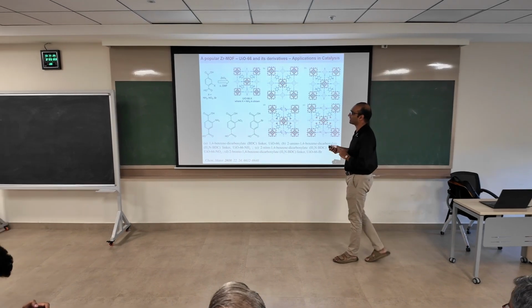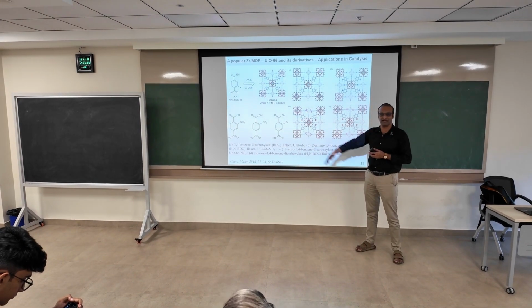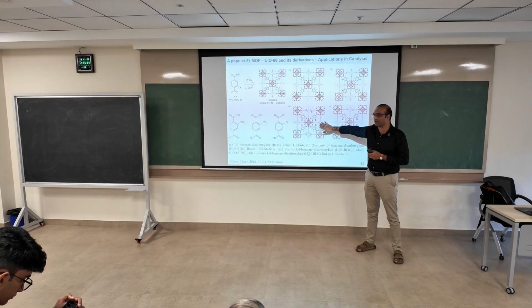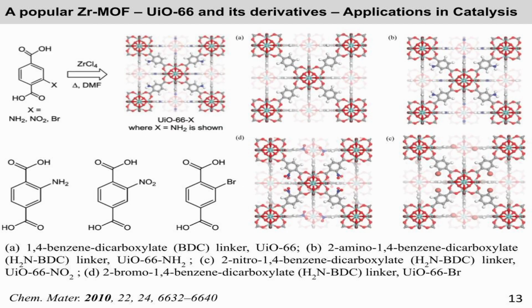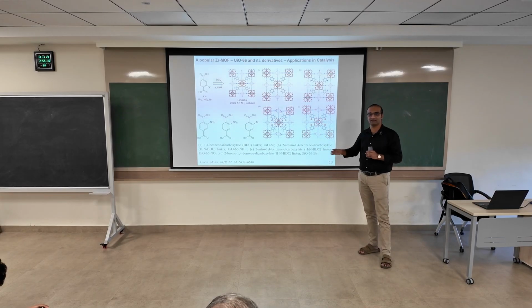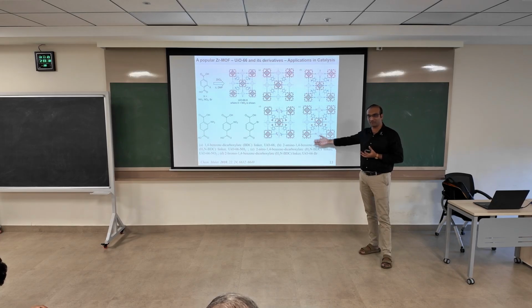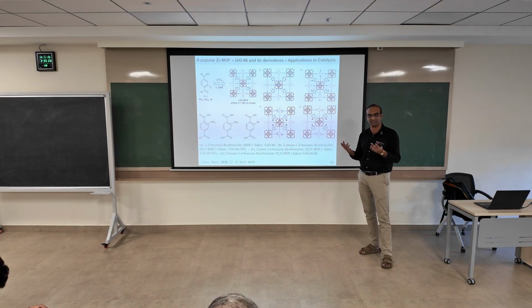You have to maximum do it like say 48 hours, 24 hours to 48 hours. And we used to make this regularly. It was not, you can give this as an undergraduate project. Anybody can make this as long as you have the chemicals. And you will almost always get the same structure. So that's one advantage of these compounds, okay? The ease of repetition, and you can validate it. Anybody can validate it and get the same material. And they will get the same values if they have access to a BET machine to find the surface area.